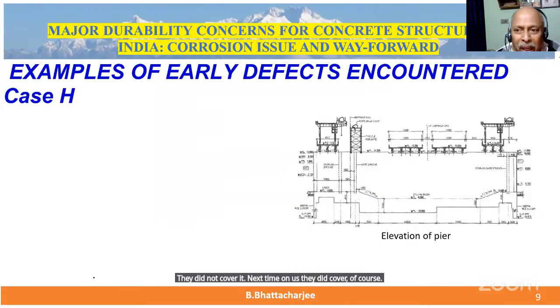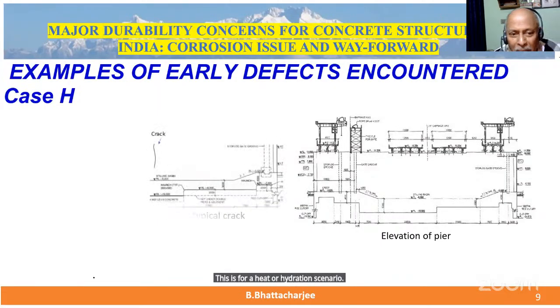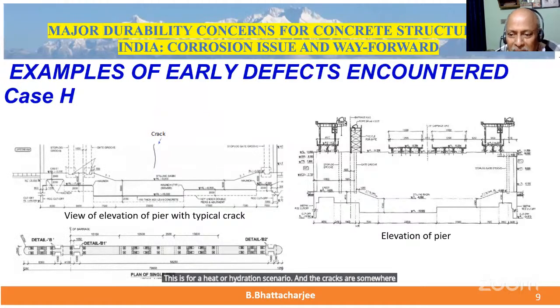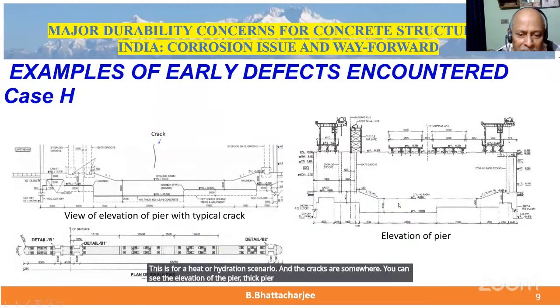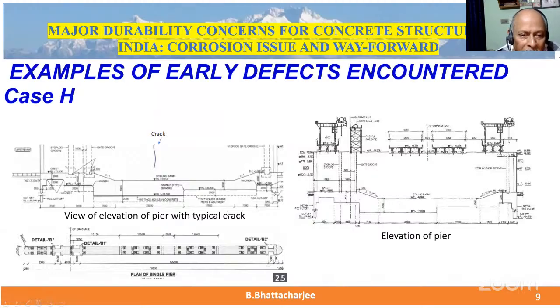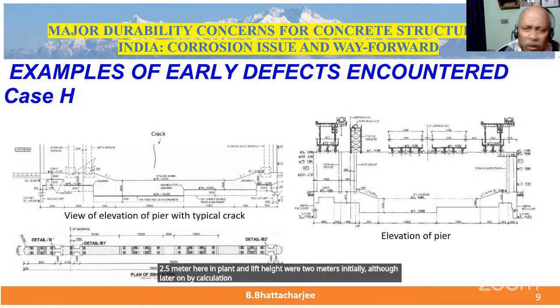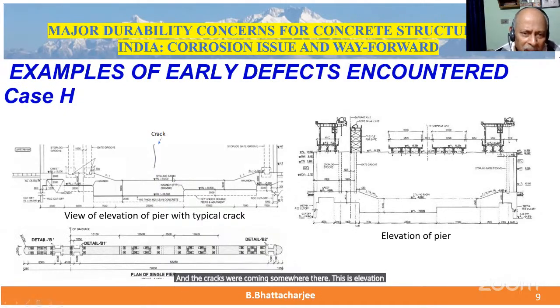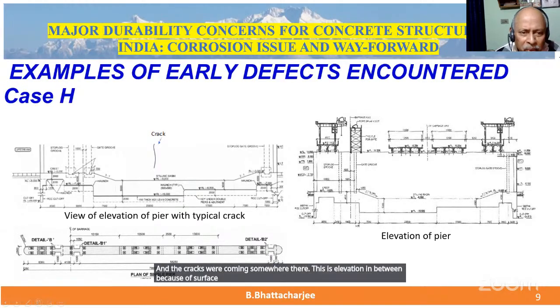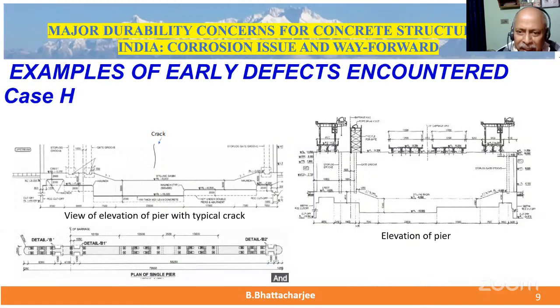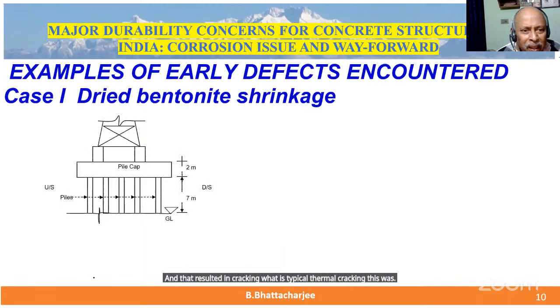This is for a heat of hydration scenario. And the cracks were somewhere, you can see the elevation of the pier, a thick pier, 2.5 meter thick pier, 2.5 meter here in plan. And lift heights were 2 meters initially, although later on they were changed by calculation or otherwise, not a very rigorous calculation. And the cracks were coming somewhere there. This is the elevation in between, because of surface cracks only. They are not penetrating through and through, rarely penetrating through and through, because the surface was cooled down. The heat of hydration core, 2.5 meters, the inside core did not cool, and that resulted in cracking. This was typical thermal cracking. They used, of course, PPC.